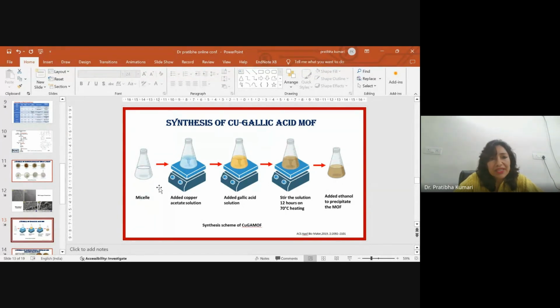Like we prepared the micelle using SDS. Then we added copper acetate and gallic acid into this solution. We stirred it at 70 degrees Celsius. This leads to the formation of the metal organic framework. Then we added ethanol to get the precipitate of the MOF. So we prepared this MOF and we added this MOF in the nanocellulose film.